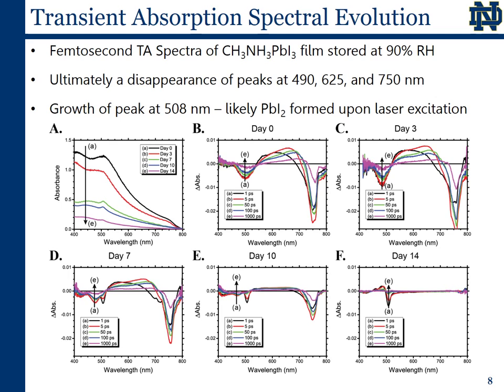Probing the excited state dynamics of the degraded films using femtosecond transient absorption spectroscopy, we see a gradual decay of the features corresponding to the crystalline perovskite and a growth of a new bleach peak at 508 nanometers. This new peak shows significant resemblance to the transient absorption spectrum of pure lead iodide.